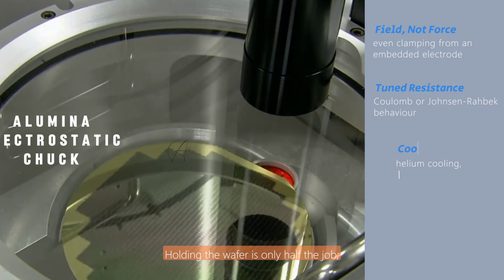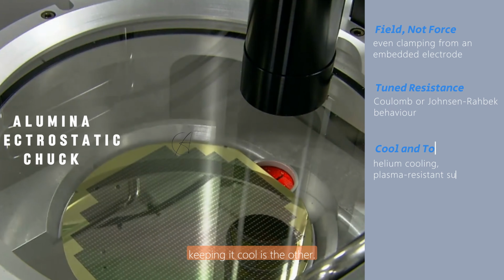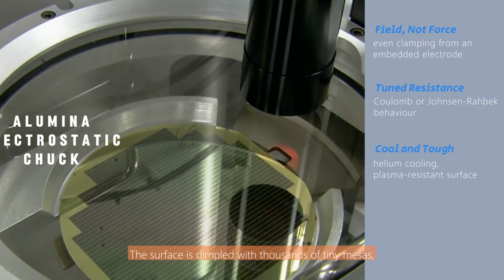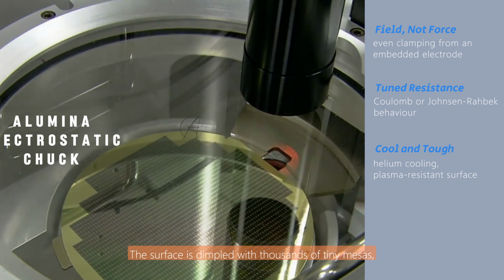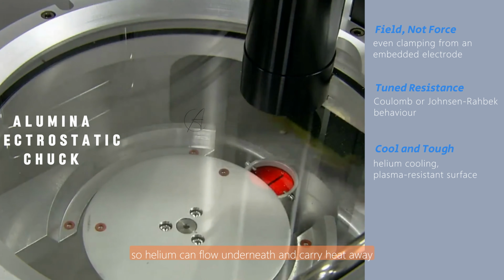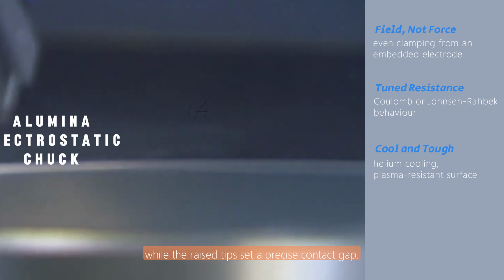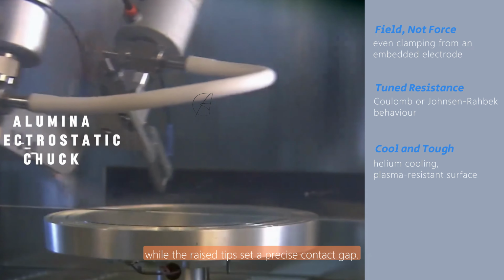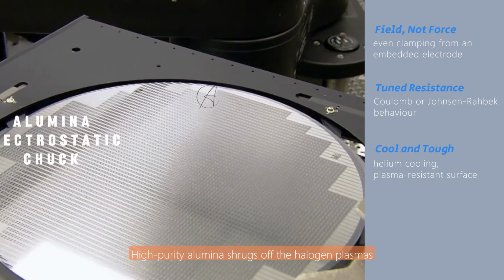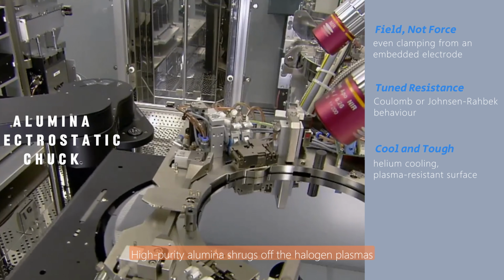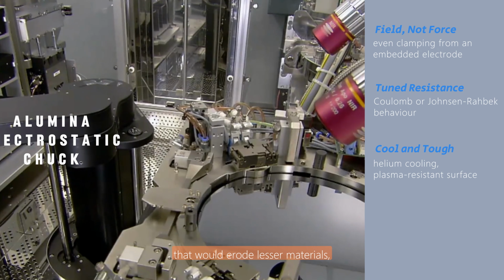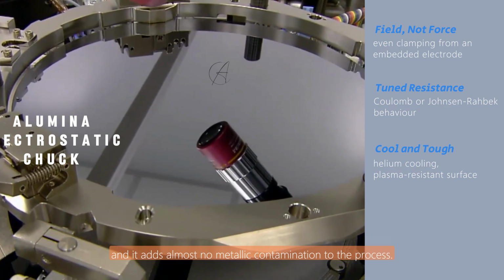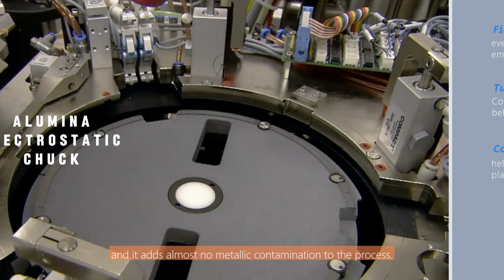Holding the wafer is only half the job, keeping it cool is the other. The surface is dimpled with thousands of tiny mesas, so helium can flow underneath and carry heat away while the raised tips set a precise contact gap. High-purity alumina shrugs off the halogen plasmas that would erode lesser materials, and it adds almost no metallic contamination to the process.